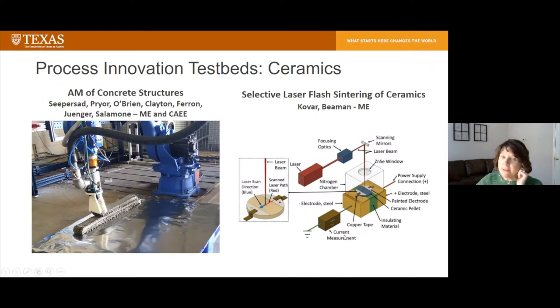Over on the right, we have selective laser flash sintering of ceramics. So this is a collaborative research project between Dr. Kovar and Dr. Beaman in mechanical engineering. In this particular case, what they're focusing on is fabricating ceramic parts. Ceramic parts are usually made using an indirect process whereby you use a laser to selectively melt a polymer to hold together the ceramic parts. And then later the polymer is burned off and the parts are then sintered, but this is slow and it can be very difficult for large parts.